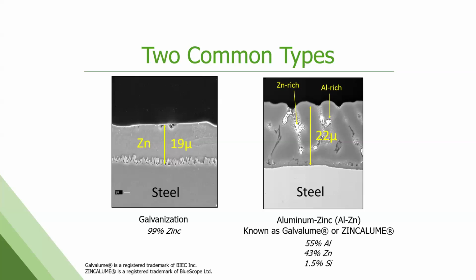The aluminum zinc composition is 55% aluminum, 43% zinc, 1.5% silicon. This is by weight, and aluminum has very low density. So there's a lot of aluminum in this final product, which is why it performs so well for corrosion protection. This is a scanning electron microscope cross-section view of actual product. On the left, you can see there's just that solid layer of zinc over the steel in galvanized. On the right, the gray areas are the aluminum, and the white areas, to me, always look like brain matter. The white areas are the zinc. So you can see there's much more aluminum by volume here than there is zinc.